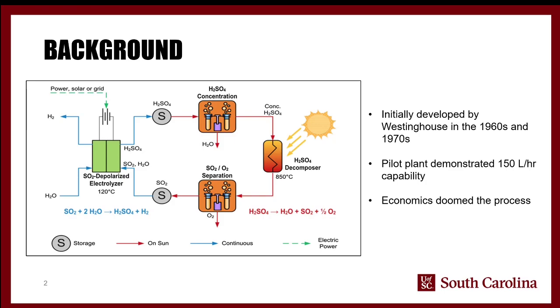They developed this two-part cycle, and it was one of a number of thermochemical and electrothermal cycles where the overall reaction is water being split to hydrogen and oxygen. What you actually have is a two-part process. One part is relatively low temperature, a sulfur dioxide depolarized electrolyzer running at around 120 degrees Celsius. The other part is actually a sulfuric acid decomposer. So what you end up with is the net reaction of water being split into hydrogen and oxygen. But what you actually have is an internal cycle. So you have sulfur dioxide and water forming sulfuric acid. You take that sulfuric acid, you decompose it, and you get water and sulfur dioxide back, but you also get oxygen. And that's the key step here.